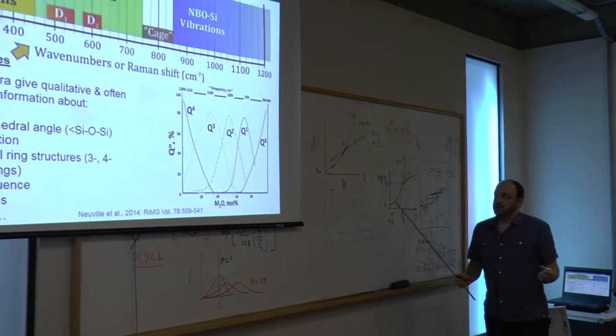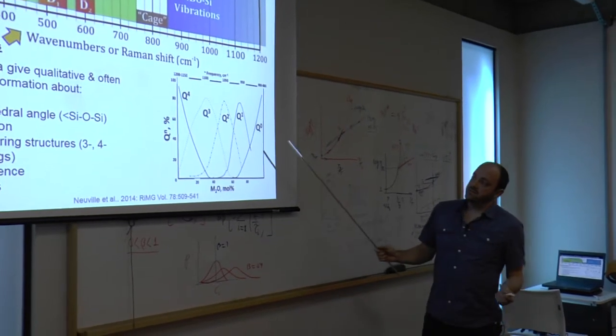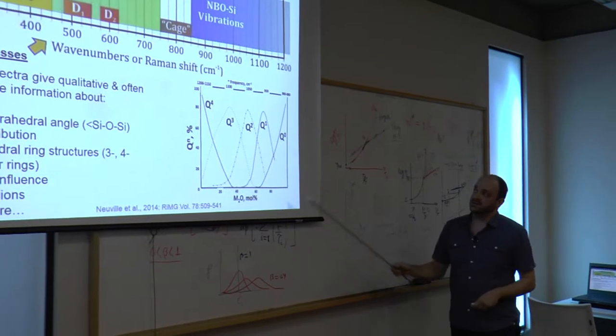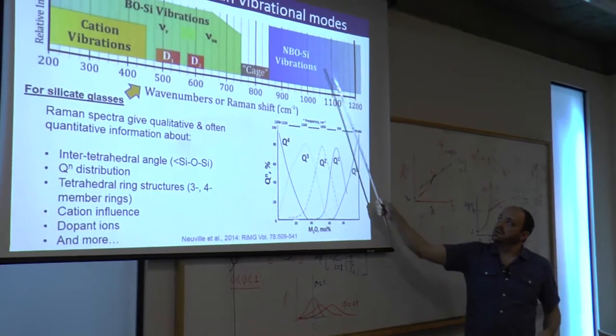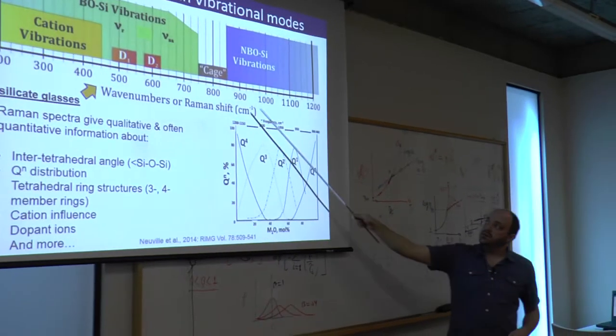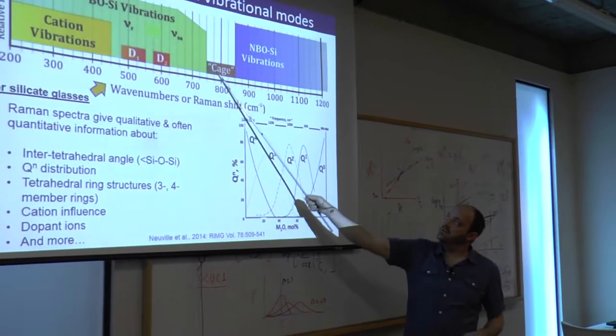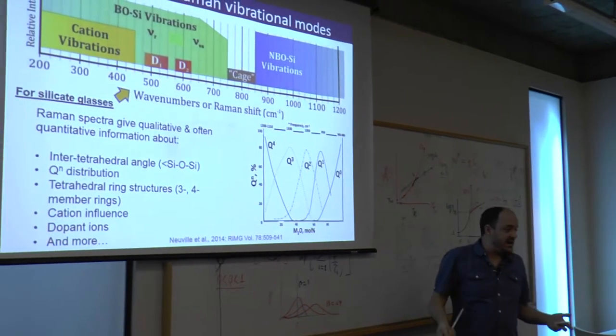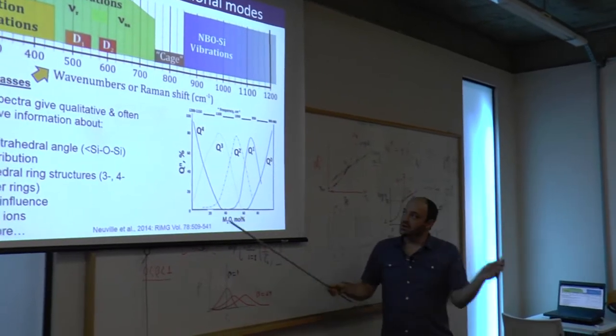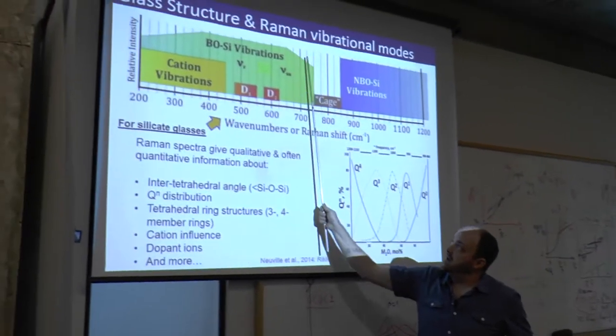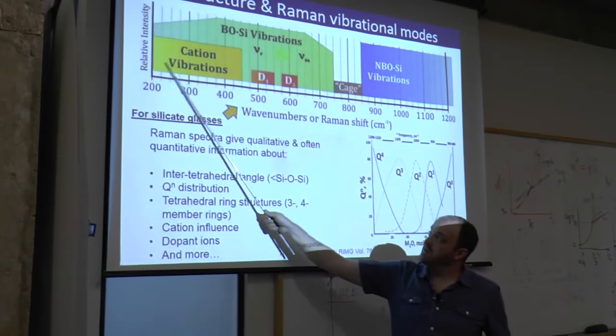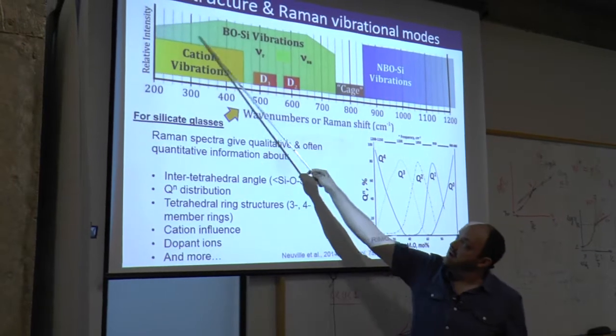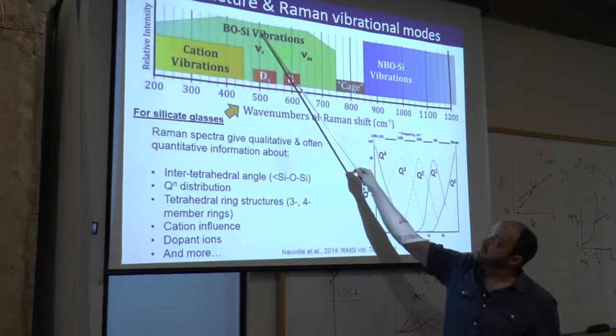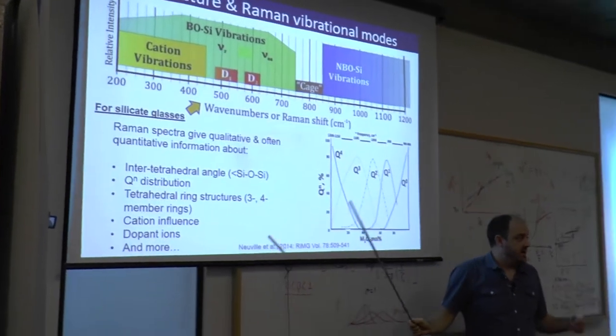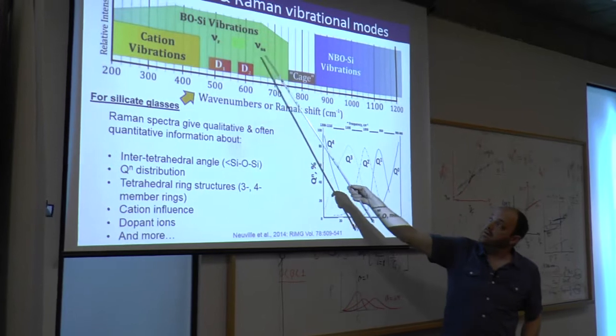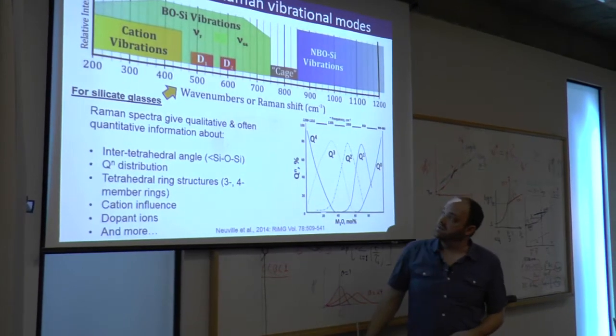So, in terms of silicates, if we look at a Raman spectra, we can talk about a few different things. The first is the QN species, and we'll see more of this later on, but they're in this high frequency range. In really silica-rich compositions around 800, there's a band. It's called a cage rattling band. It's not really well defined, so I'll leave it at that. But we also have vibrations down here from the bridging oxygens, and these span quite a wide range. You've seen in pure silica, they have a large band here, 200 to 500, and as you go to more metasilicate and more modifier-rich compositions, these BO vibrations go to higher wave numbers.